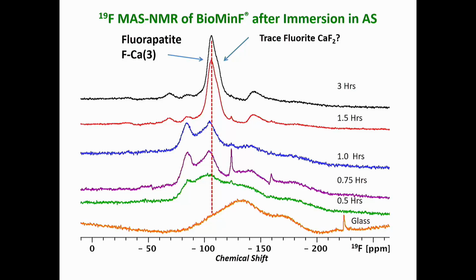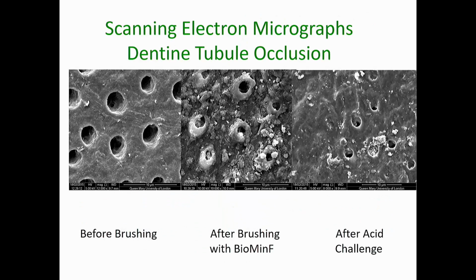So what we're looking for is this FCA3 site, and this has a chemical shift of -103 ppm in the NMR. What we can see is, in the original glass, we've got a broad spectrum, the orange spectrum at the bottom, which is glass. Then even as short as 30 minutes you can see a broad peak developing which becomes sharper with time and has a chemical shift of -103, which shows us that we're forming fluorapatite.